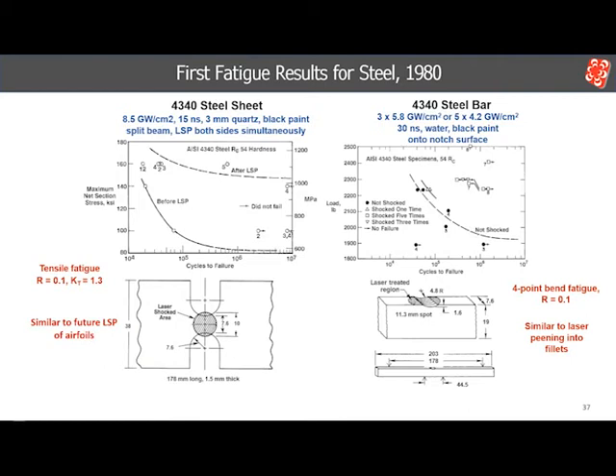Laser peening the surface of the notch in the bar using black paint and water overlays, the specimens were given 1, 3, or 5 shots. With 5 shots, the fatigue strength was increased at least 30%. Tests at higher loads couldn't be completed because the loading pins were deforming the surface of the bar, so the tests were discontinued. It was clear that laser shocking was very effective in increasing the fatigue life of hardened steels.